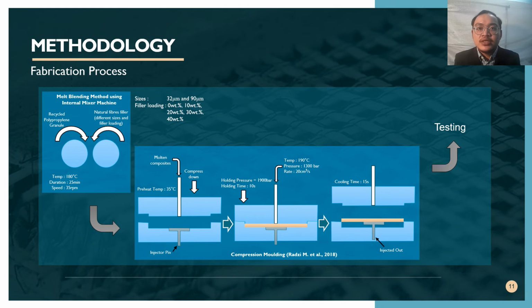For the compression molding, the parameters are taken from the study done by Razak et al. in 2018. The mold is preheated to 35 degrees Celsius, then the molten composite is injected into the mold at a rate of 20 cm cubed per second, a pressure of 1300 bar and a temperature of 190 degrees Celsius. The mold is held at a pressure of 1900 bar for 10 seconds. Finally, the composite is ejected from the mold and cooled down for 15 seconds. Then, the fabricated composite will go through testing.